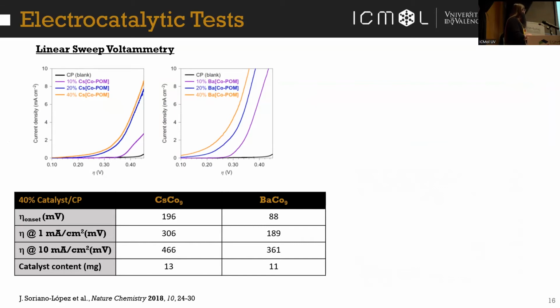Here we can see that by increasing the amount of the catalyst inside the blends of the modified carbon paste electrodes, we increase the catalytic activity, and we compare the cesium salt with the barium salt. We were quite surprised to see the barium salt gave a really good onset overpotential, which is the potential at which we start the reaction. We were actually surprised to see that the barium was much better than the cesium. And it gives an 88 millivolt overpotential, which at that time was the lowest overpotential reported. And I think it is one of the lowest reported right now in acidic conditions.